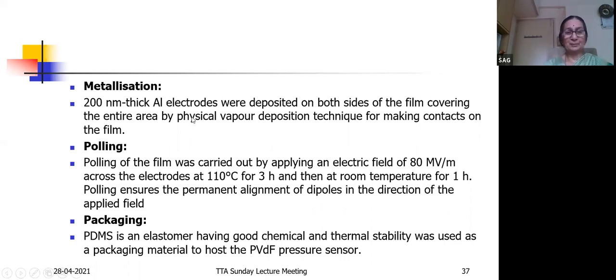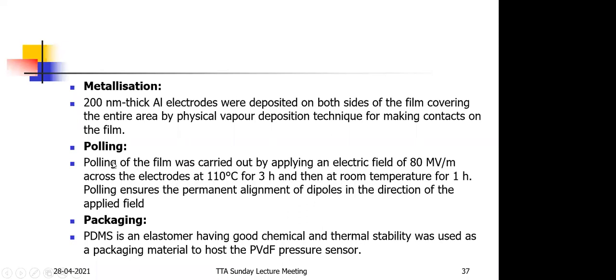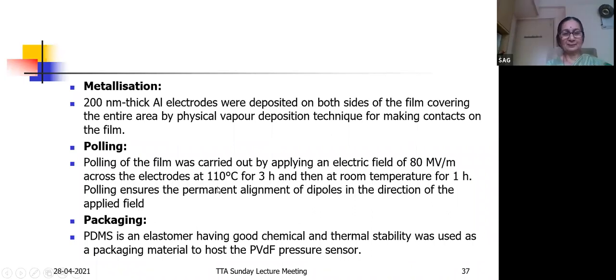Now, these films, we wanted to increase the beta value still further. So the film was cooled, and poled at 110 degrees centigrade for 3 hours. The packaging of the film was done in PDMS, an elastomer which has good chemical and thermal stability, and it's used as a packaging material for PVDF sensors.